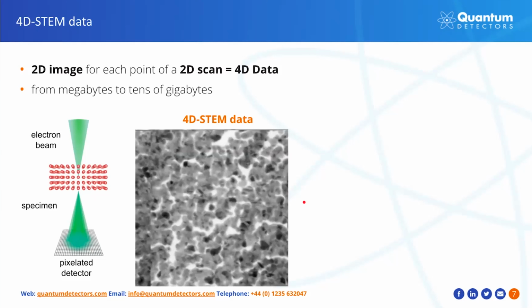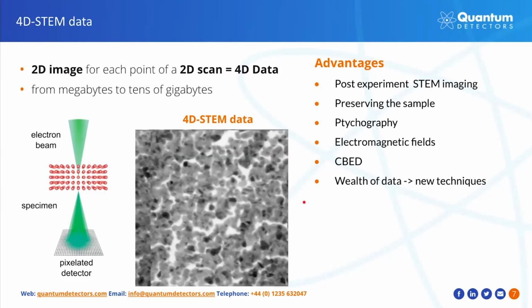The standard signals can be generated with more sensitivity because we can choose the geometry and the size of the detector after the experiment. This can be beneficial for complex samples where one size of the detector does not fit all, but additionally, we only need to expose the sample once. Therefore, we can preserve it better if different imaging conditions are needed. The wealth of information offers additional opportunities, which would not be possible without four-dimensional datasets.